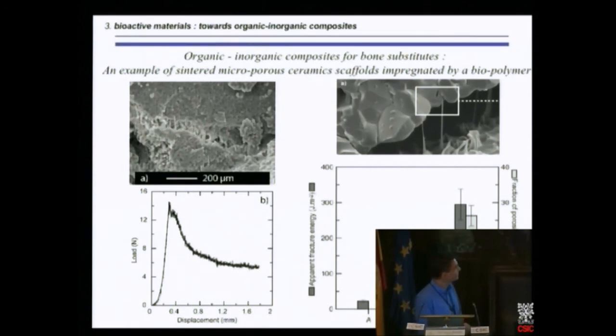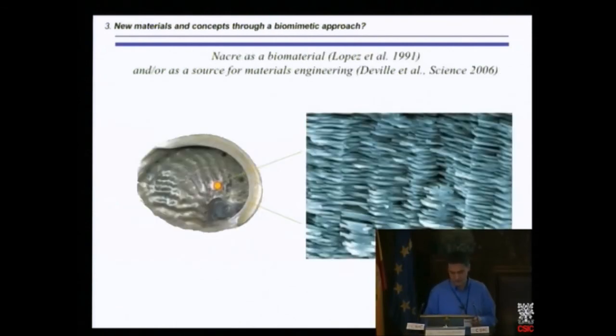Let's have a look at the results. It's more than one order, almost two orders of magnitude in terms of apparent fracture energy. So we cannot increase the strength. The strength is the same, but what is important is that the energy to failure is much more important in this type of inorganic compounds.